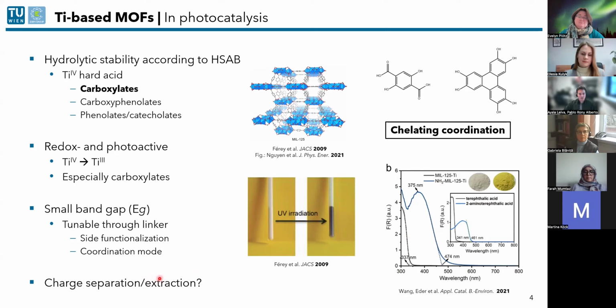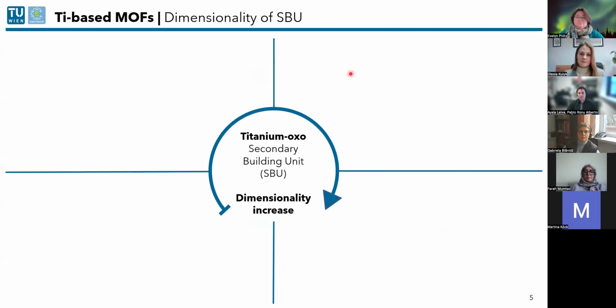This component has to do a lot with structure. So if you think about these structures, to extract the charges, in the case of MIL-125, the charges would have to hop from SBU to SBU to be ultimately extracted. But if you change the structure of the MOF, you can improve this charge separation and extraction. And this brings me to the next slide. So the dimensionality of the titanium oxo secondary building unit.